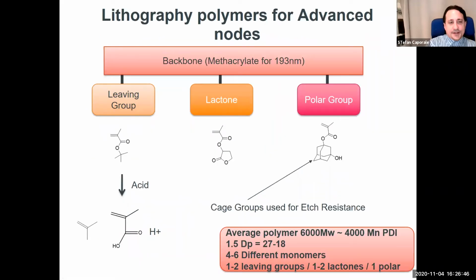Moving to the more advanced nodes, we had to move to a methacrylate backbone. The styrenic backbone is very absorbent at 193, so that doesn't work. And so we had to go to a methacrylate platform. Here we then went with more of a pendant system, and we have many more monomers we have to combine. So we have a leaving group that protects this carboxylic acid. So again, you have a leaving group that you can then expose to acid and make into an acid.